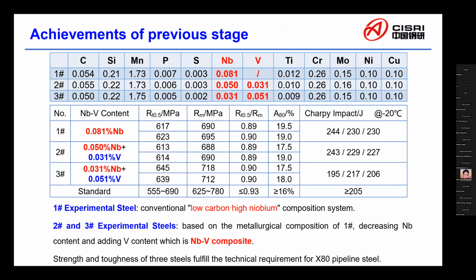Here are the research results of the previous meeting. 3 kinds of steels with different niobium and vanadium content are obtained in the lab. The chemical composition of number 1 steel is the same as X80 pipeline steel manufactured in steel mills in China, with a conventional idea of low carbon and high niobium. But when it refers to number 2 and number 3 steel, based on the metallurgical composition of number 1 steel, the content of niobium is decreased and vanadium is increased, which is the so-called niobium and vanadium composite.